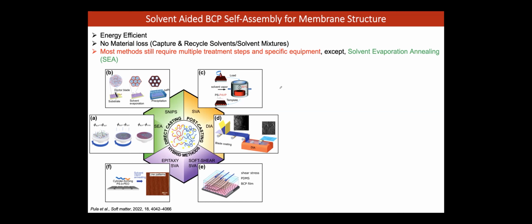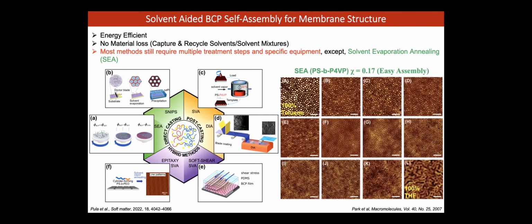Then you typically would need to treat the surface of the substrate or put some shear on it to align it and so on. But can we just use what's called solvent evaporation annealing? This is SEA. You just pick a solvent that gives you the right orientation from the get-go. It's the simplest, easiest, and you can do roll-to-roll processing. There have been a lot of studies on SEA, and we wanted to modify it to make it more versatile in controlling pore dimension and so on.